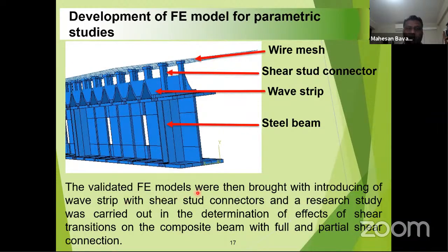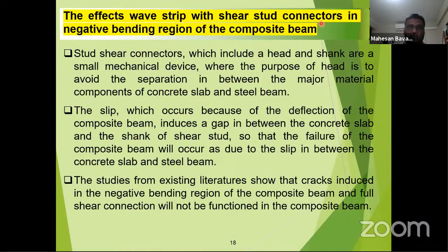The validated finite element models were then used with the introduction of wave strip with shear stud connection, and a research study was carried out to determine the effects on shear transmission of the composite beam with full and partial shear connection. So the effects of wave strip with shear stud connectors in the negative bending region of the composite beam. Stud shear connectors, which include a head and shank, are small mechanical devices, where the purpose of the head is to avoid separation between the major material components of the concrete slab and steel beam. The slip, which occurs because of the deflection of the composite beam, induces a gap between the concrete slab and the shank of the shear stud, so that failure of the composite beam will occur due to the slip between the concrete slab and steel beam.